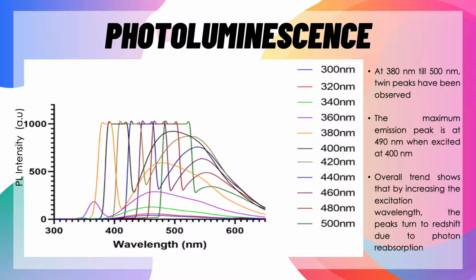So this shows that the nanoparticle is excitation dependent. Referring back to the FTIR results, when you have the presence of C double bond O and other carboxylate groups, it increases the presence of oxygen on the surface. The increase in oxygen groups tends to lead to surface defects. Therefore, that's why we have the redshifted emission.